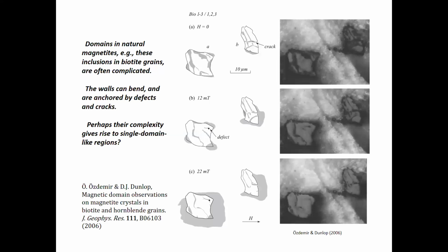And in the 2000s, she moved on to looking at much smaller magnetite grains. These are inclusions within biotite. And here the patterns get much more intricate and complicated. You can see imperfections like a crack at the top, a little harder to resolve in the photographs. There's a point defect of some sort in the middle picture. And when fields are applied, this is a set of increasing fields, these walls bend, which they shouldn't do in magnetite. This creates a whole lot of demagnetizing energy. That shows just how firmly these walls are pinned by appropriate defects, that you can actually bend the wall and produce enormous demagnetizing energy.